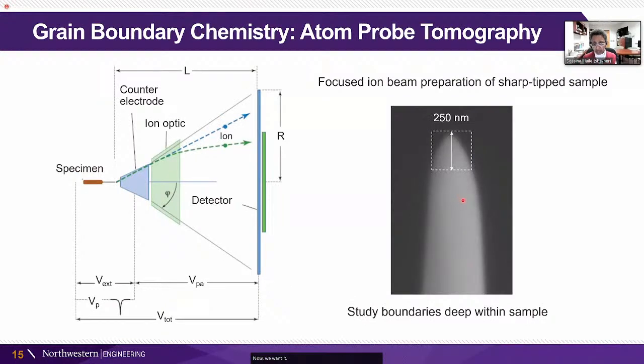All right, so this is the range in interface potentials. Now, we wanted to understand, as I said, whether or not there was any contribution possibly from impurities at those interfaces. When we did that electron holography, we also did electron microscopy chemical analysis, and we could not detect any impurities. In fact, we couldn't even detect our dopant, which was there at the level of 0.1%. However, atom probe tomography is more sensitive even to the chemical analysis, to the presence of impurities.